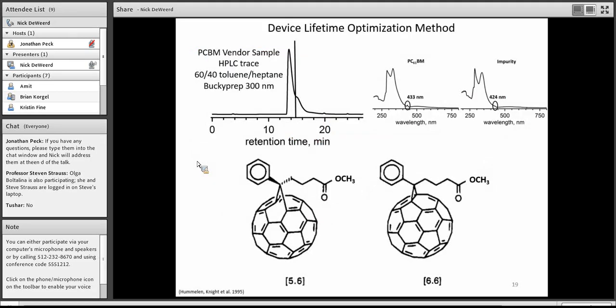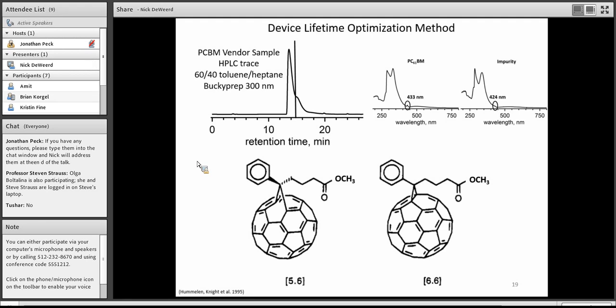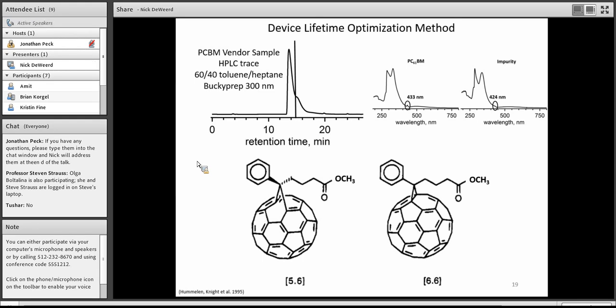You can see that I found something that worked reasonably well. That's 60-40 toluene-heptane by HPLC separation using the Bucky Prep stationary phase, which is a pyrene stationary phase bound to silica. You can see that I was able to separate the bulk of the PCBM from this impurity. Then by analyzing the UV-Vis data, as well as those chemical shifts, I determined that the impurity was actually this 5-6 isomer.